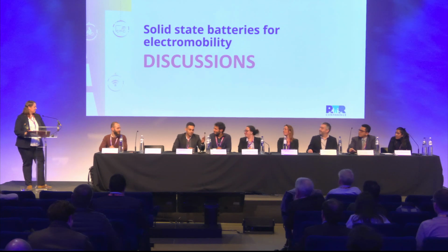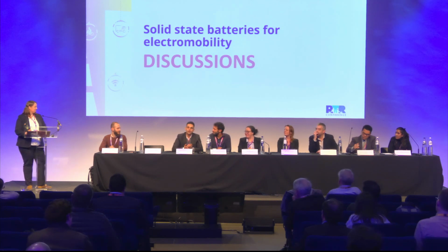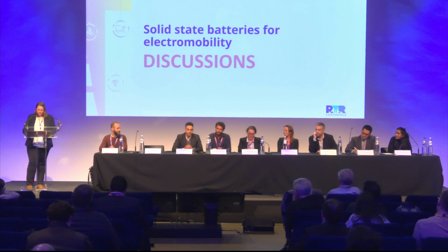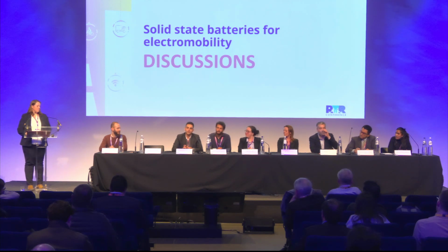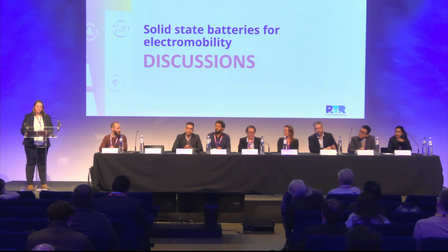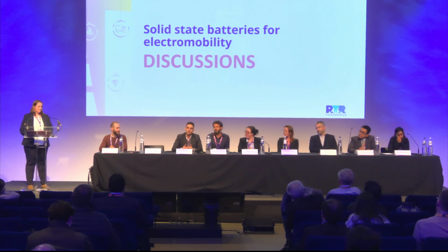Okay, Arash. Yeah, so from my understanding, at least in SUBLIME, this was the case. For example, the interface we can engineer, for example, for the cathode to the solid electrolyte. So we can coat the cathode and it works with the solid electrolyte. With the lithium anode, we can also apply coating and it works with the solid electrolyte.